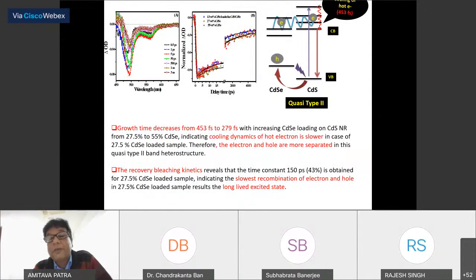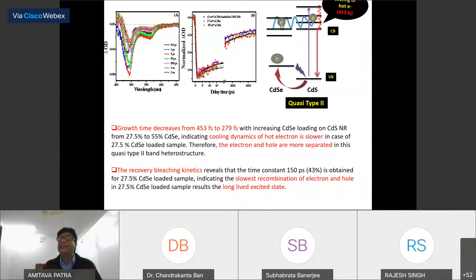I'll not go into the detail of the mechanism. Now, by using ultrafast spectroscopy, we try to understand all the relaxation processes, the hot cooling process that takes place in 453 femtoseconds, because we have seen that cooling dynamics of hot electrons is very slow in certain compositions. That's why electron and hole are more separated, and if they are more separated, then that electron and hole can be used for reduction and oxidation purposes, or they can generate a photocurrent. So ultrafast spectroscopy can give you an idea of what kind of relaxation process it is. That's why the spectroscopy part is very important in material.